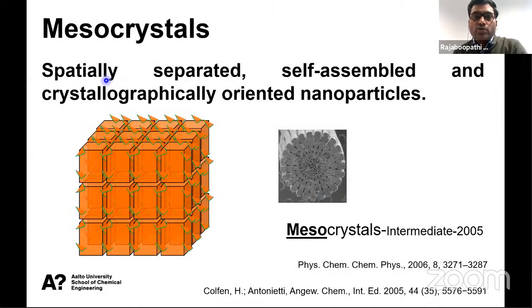So mesocrystals, how to define mesocrystals? It is spatially separated, self-assembled, and crystallographically oriented nanoparticles. You can see there is some aggregation. In the aggregation, there is no crystallographic orientation. If you diffract using X-ray, it won't diffract like single crystals. But these mesocrystals, even though it is an attachment of particles, when you use X-ray, it will diffract like single crystals. That's why I used the term crystallographically oriented nanoparticles.